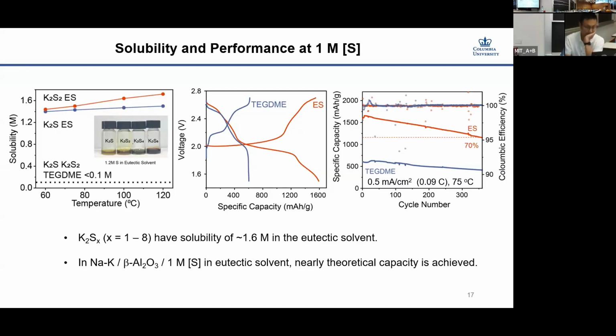And you can see here, it actually can reach 1600 mAh per gram capacity. So that indicates that we have very good kinetics, almost fully utilizing all the sulfur inside. In contrast, for the TGDME, you can only get 600 mAh per gram capacity. The cycling is reasonable. This cell gets 350 cycles, with expected retention of about 70%. So the TGDME shows better cycling, but the capacity is much less.